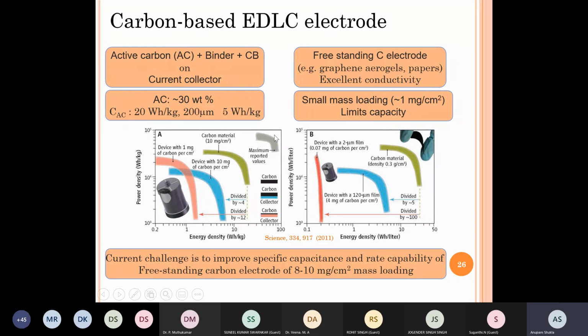So these are the values which are reported in literature. So you'll see 20 watt-hour per kg, 30 watt-hour per kg. Those are mostly for the active material. However, if you come with the active material which has to be loaded onto the current collector, then one gets to values which are here.